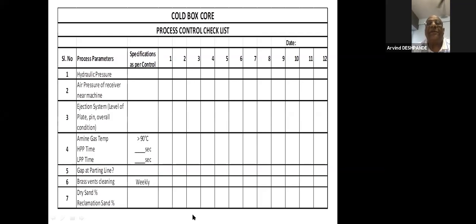Then comes the air pressure. Air pressure specifically I have mentioned near the receiver of the machine. And one thing I would like to add, the air should not contain drops of moisture. A filter should be there. Then the third point is the ejection system: level of pin, plate, overall condition. These are most important because otherwise the core will not come out or damage will occur on the core. Then the next point is amine gas temperature. It should be above 90 degrees centigrade. Then HPP time, LPP time. These are also important. Amine gas temperature is most important.